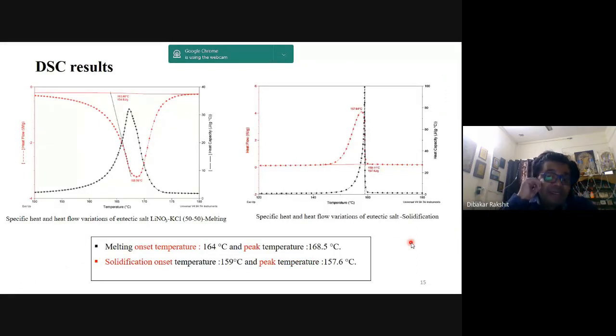So these are some of the representative results of the differential scanning calorimetry which we conducted over this lithium nitrate and KCl binary eutectic. You can see that the onset of melting starts at 164, and then finally the peak reaches 168. And when it is going the other way, the onset of solidification starts at 159, and finally it reaches its peak at 157. However, a standard phase change material, if it is maintained at a constant temperature, should reach the onset for melting and solidification exactly in the same temperature range, but it is not happening that way.